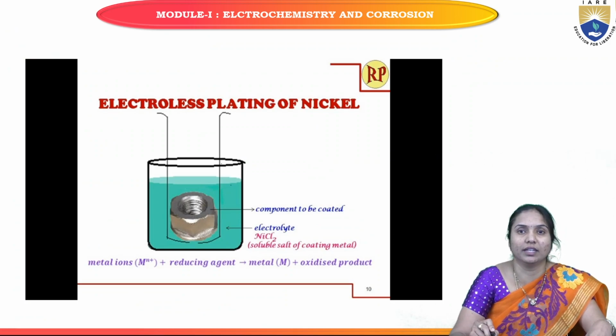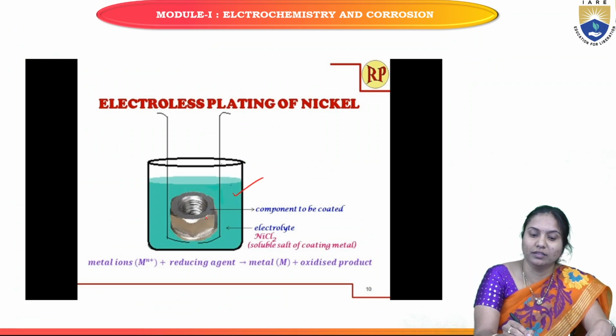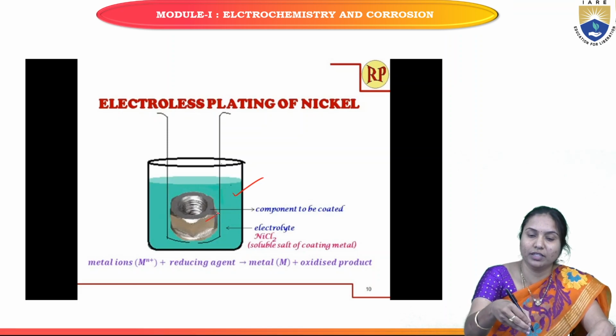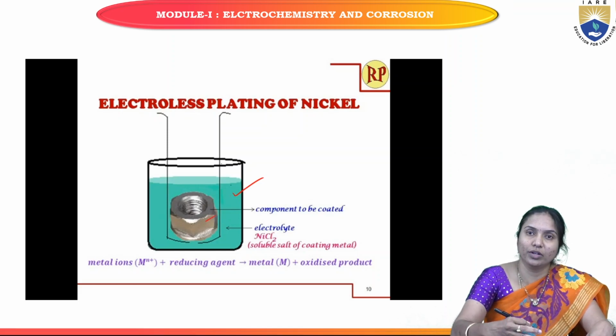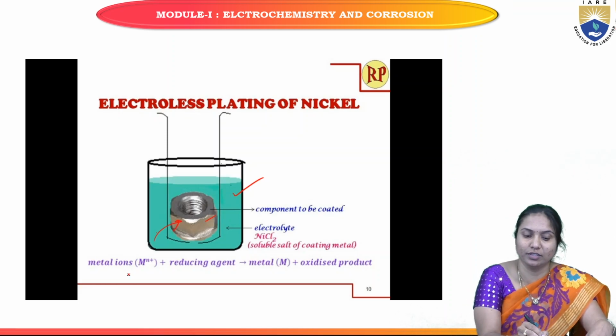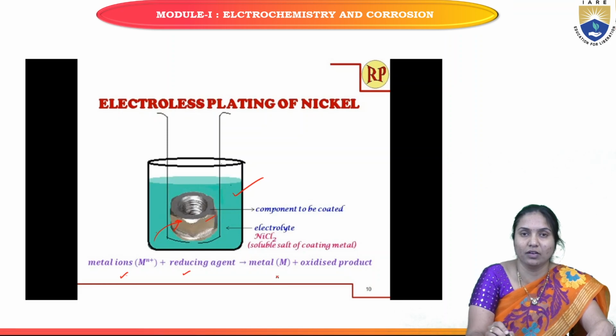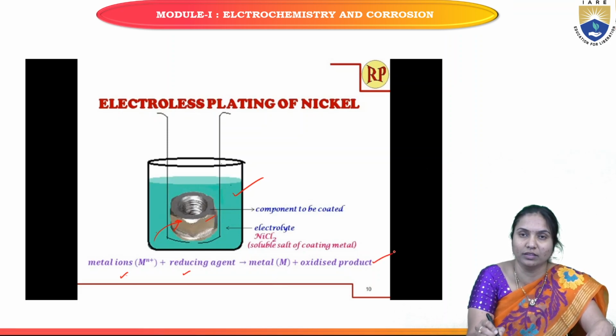So this is the electroless nickel plating. This is the coating bath. This is a base metal object. When we put it in this coating bath, the nickel coating forms on the metal surface, and the reducing agent reduces the coating metal ions and deposits the nickel coating on the base metal. So this is the principle involved. When we add the reducing agent, it reduces the metal ions, and the metal is deposited on the base metal surface, along with the oxidized product. This is the principle involved in electroless nickel plating.